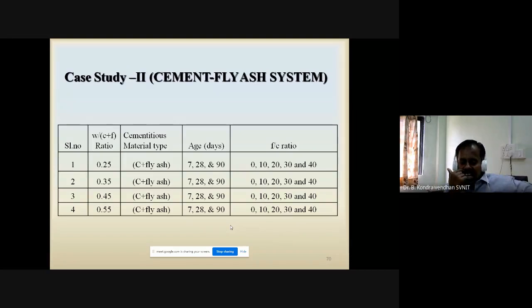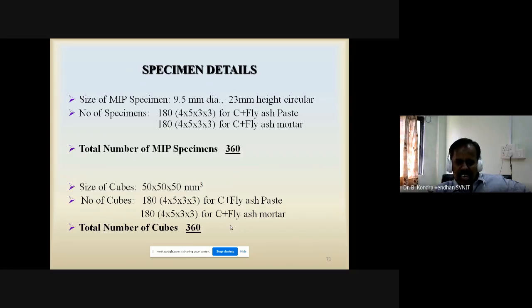And we replace the cement with 4 different percentages: control, 10, 20, 30, and 40. That is the F by C ratio, I can say. So that's how we started this cement fly ash system. Here also we have done a number of tests on the cement fly ash paste and cement fly ash mortar. We also determined compressive strength.